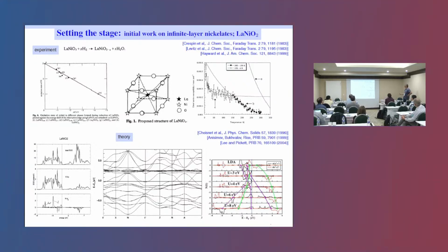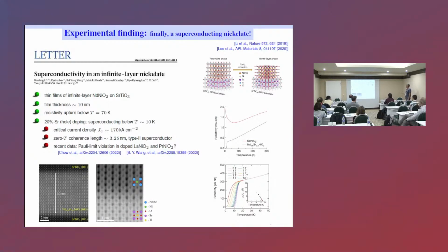Then there was, as already mentioned, the Anisimov work that put this into a cuprate context, but then there was the follow-up work by Lee and Pickett, who claimed that there is this self-doping band that was highlighted in this work, and also said that nickel d_z^2 takes on quite some importance in this compound, although still from a DFT plus U static correlation scheme, but still saying that this nickel 1+ is maybe different from the cuprate analogue.